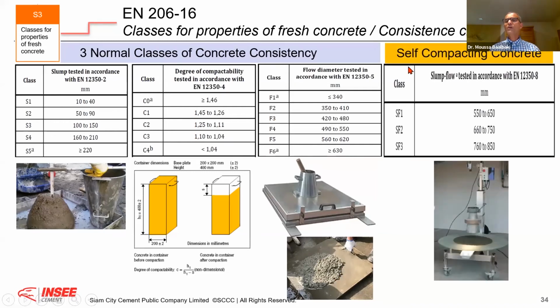And there is also what we call self-compacting concrete. These are concrete normally. They flow and they go. You don't need to consolidate them. Therefore, there is a special test for them. They use the Abrams cone. You fill the cone, you lift the cone, but without vibration, without compaction, and you measure the slump flow. We call it slump flow. Here also you have class of consistency. You see, it's not as simple as a person can consider. Therefore, you have class of consistency, and within the class of consistency, you have the type, how you measure the consistency of your concrete. Okay?